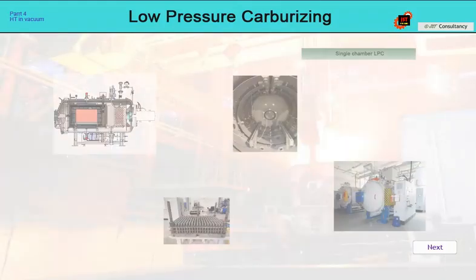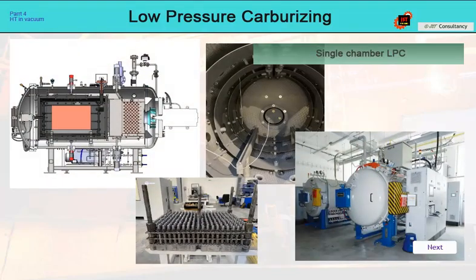There can be a whole range of low-pressure carburizing equipment. We can start with single-chamber furnaces, but I consider them unsuitable for this technology. First, we must reheat the carburizing chamber every cycle, and at the same time, the heat capacity of the heating chamber reduces the cooling rate where I need it most. In the case of quenching in gas stream after carburizing, this is a device for testing rather than production.